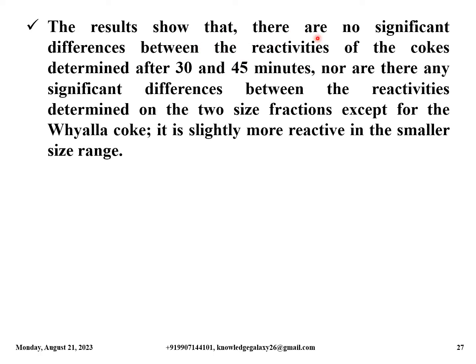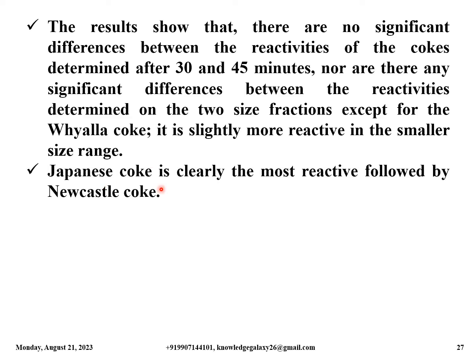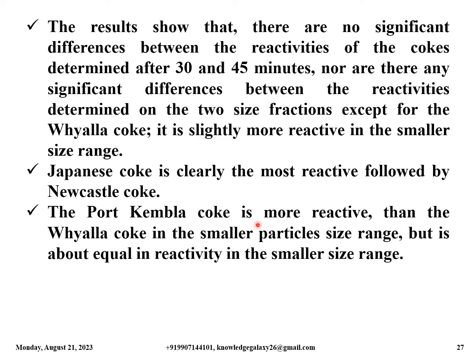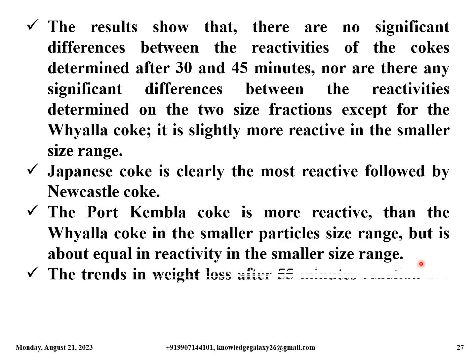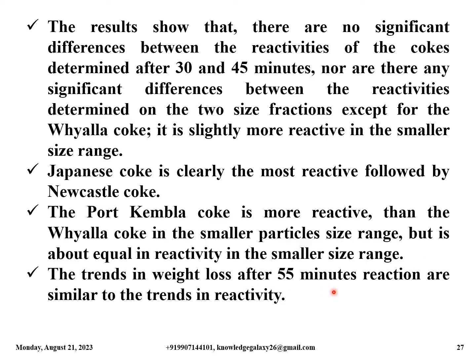The results show that there are no significant differences between the reactivities of the cokes determined after 30 and 45 minutes, nor are there any significant differences between the reactivities determined on the two size fractions, except for the Whyalla coke. It is slightly more reactive in the smaller size range. Japanese coke is clearly the most reactive, followed by Newcastle coke. The Port Kembla coke is more reactive than the Whyalla coke in the smaller particle size range, but is about equal in reactivity in the larger size range. The trends in weight loss after 55 minutes of reaction are similar to the trends in reactivity.